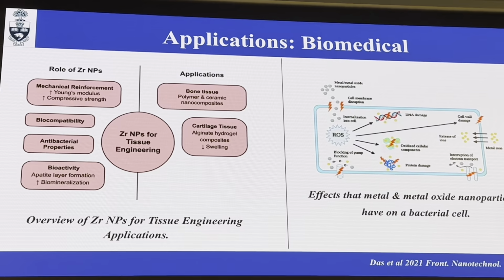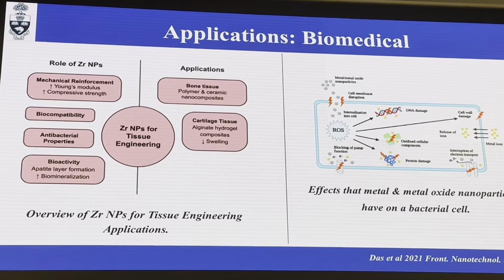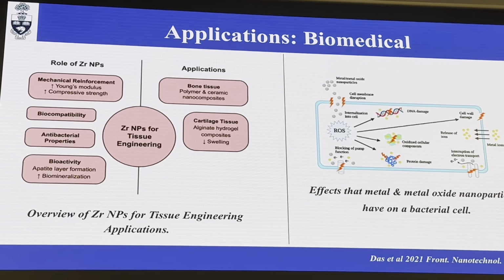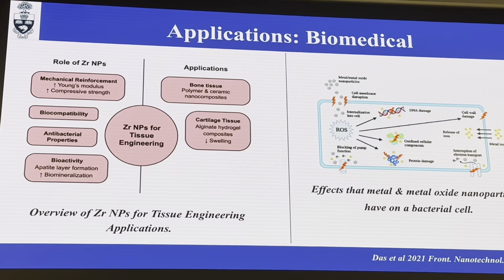They also have bioactivity that promotes apatite layer formation, supporting biomineralization and tissue regeneration. These properties can be leveraged in bone tissue engineering, where zirconia is used in polymer ceramic nanocomposites. In cartilage tissue scaffolds, especially in hydrogel-based composites, it helps in reducing swelling and improves mechanical performance.